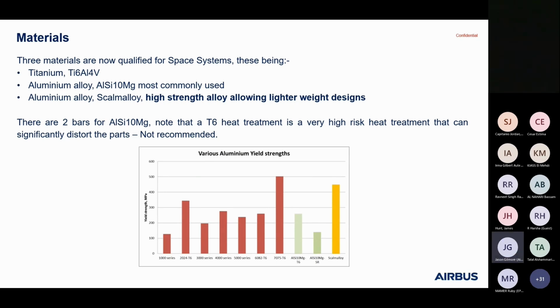Materials that are now qualified within Airbus Defence and Space, we've got titanium 6Al4V. Titanium additive products form perhaps less than 5% of the total additive parts that we've got flying. Aluminium silicon 10 is most commonly used, and in 2018 we went round a bit of a tour of Europe to find who had Scalmalloy to do our qualification with, and we had a bit of an open competition, and we selected a Belgian company called AnyShape to do that qualification.